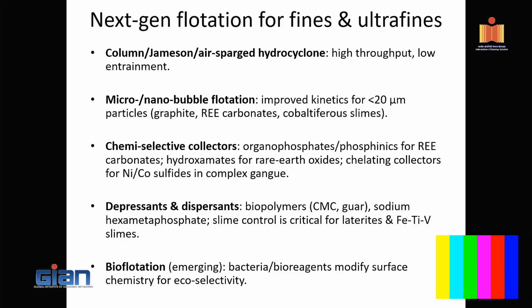what is the difficulty for critical minerals having fines and ultrafines for flotation to act upon? So the one is, let's say you take a mechanical flotation, right? You are actually inducing certain stirring to bring the particle close to the bubble. But in the process, even if you stir with impeller-based rotation of the fluid, a particle of 10 micron, for example, would not come closer to the bubble. Rather, it follows the water path, because 10 micron particles are very much influenced by local turbulence. If I have high eddies created near the impeller, my particle never comes to the bubble surface, but rather moves along with the water and gets recirculated.